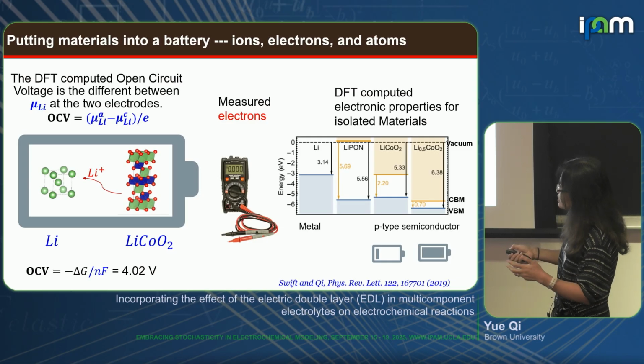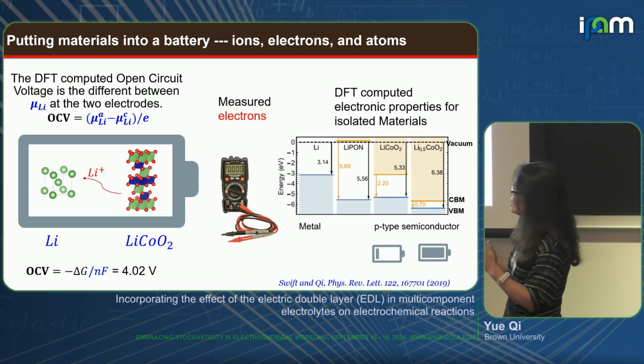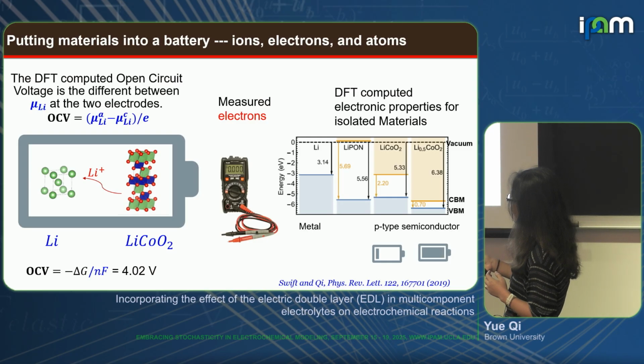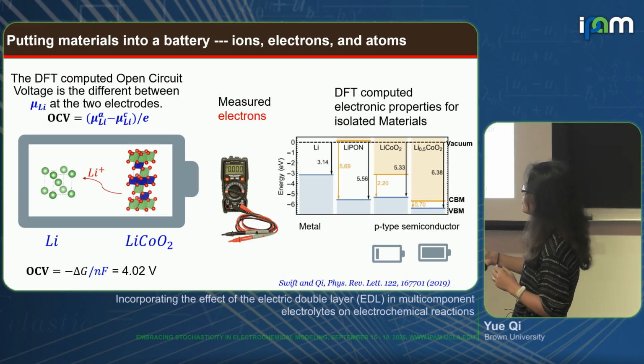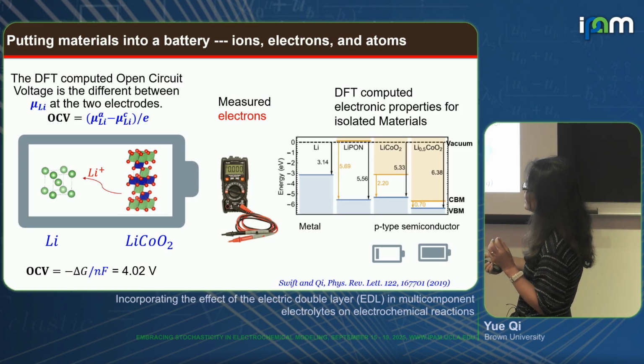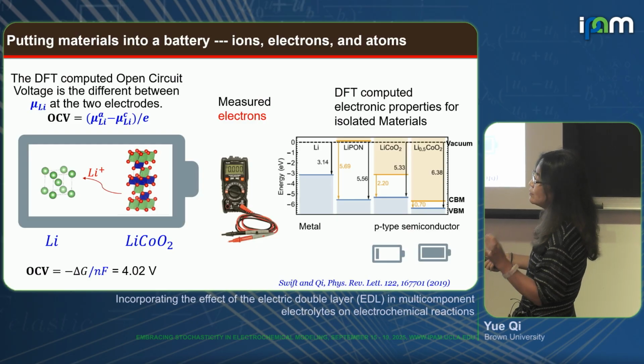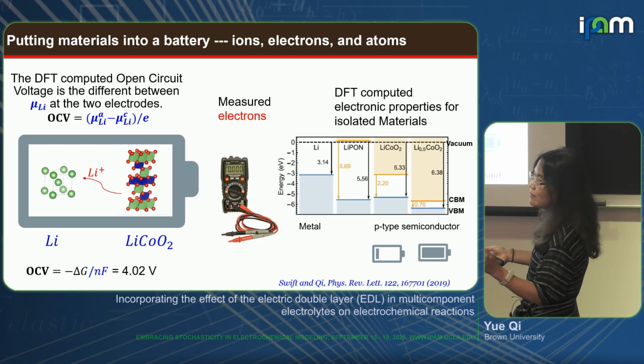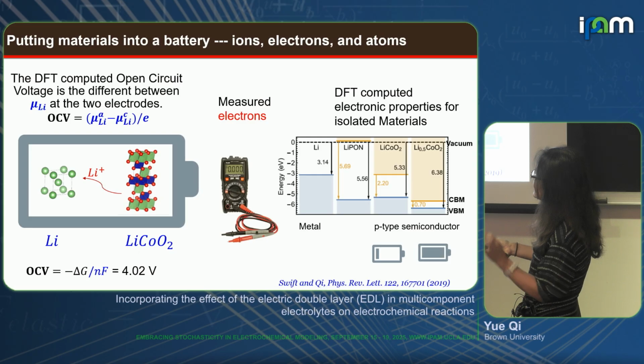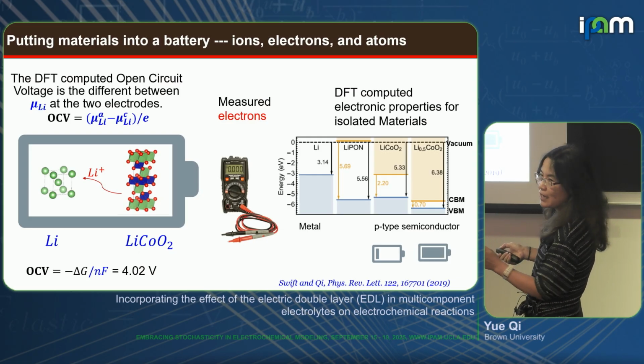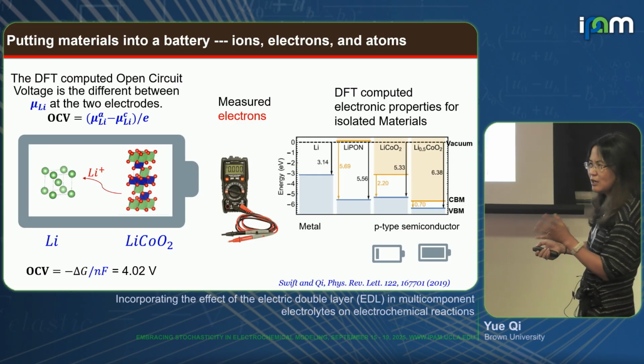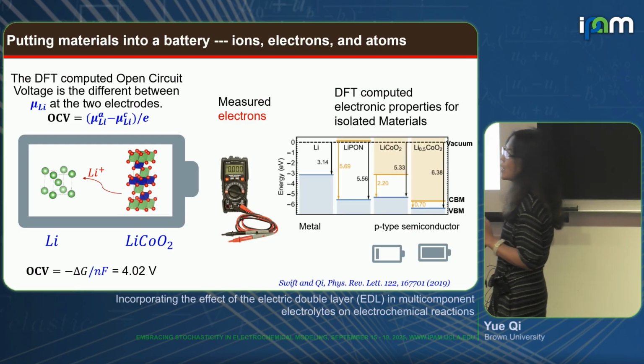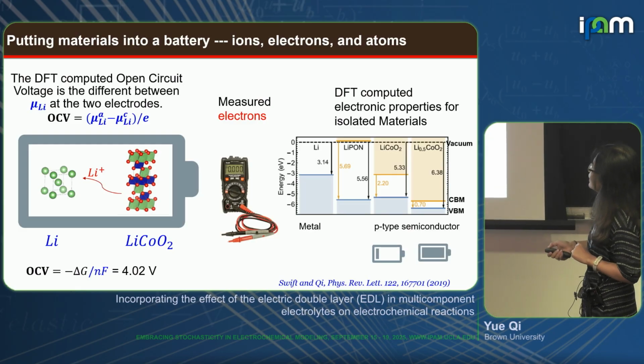In Materials Project, on average, we're talking about the overall thermodynamic driving force for a battery is the chemical potential difference of these lithium species from one phase to the other, right? So lithium to lithium cobalt oxide. You can calculate from DFT, you're right close to the truth and experimental values for volt.